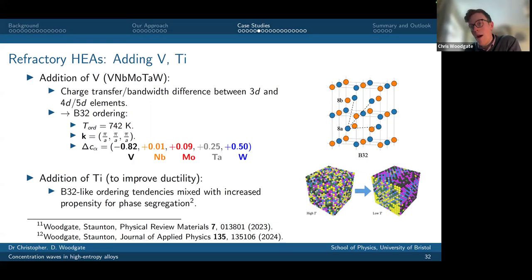We did some work looking at what happened if you included titanium, because some people include titanium experimentally to try and improve the room temperature ductility of these materials. And what we found there was that actually you got these B32 ordering tendencies, as you did with vanadium, but also there was real competition between ordering and phase segregation, which is described by a concentration wave with wave vector 0, the zero vector. Okay, so that was kind of interesting.